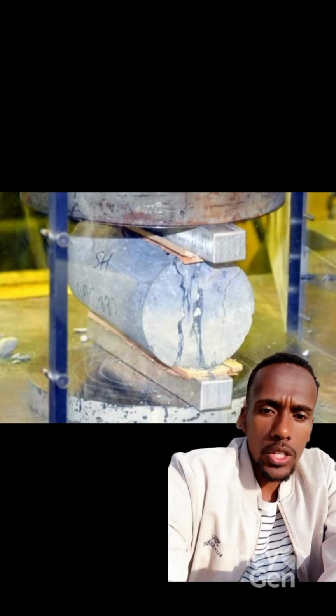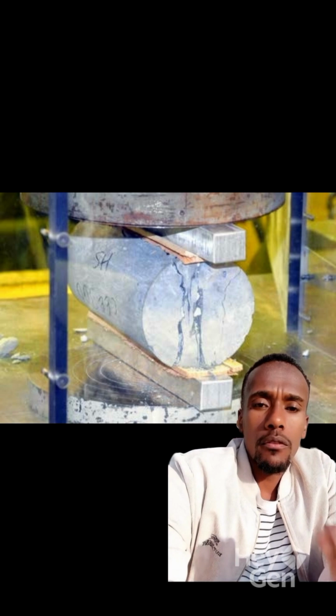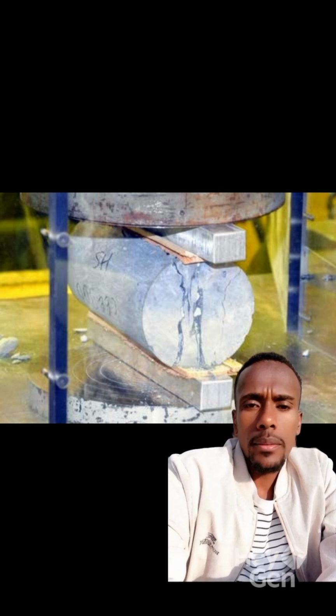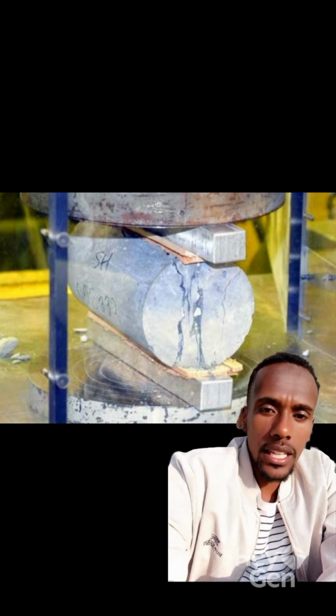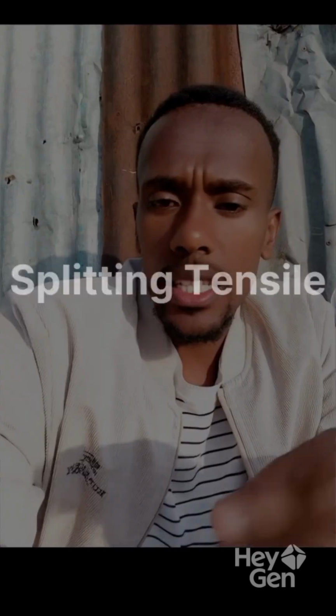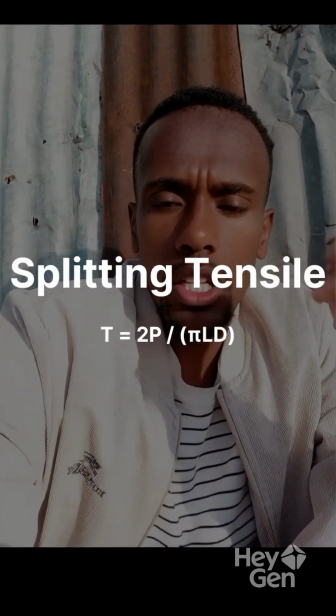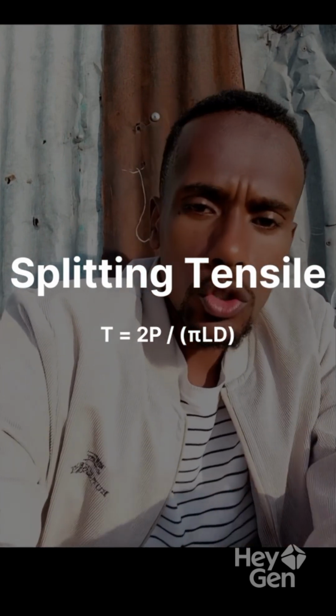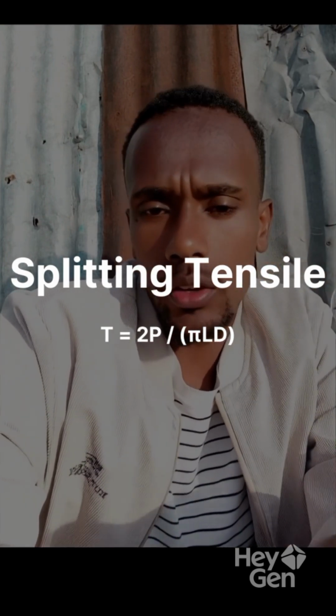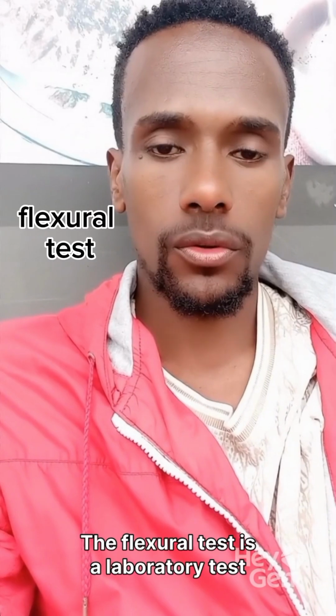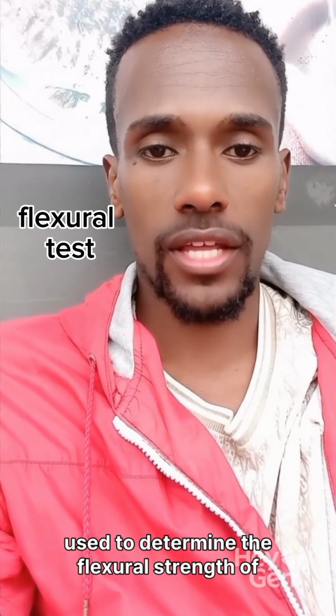The procedure involves curing the concrete cylinder for 7, 14, or 28 days, then placing it horizontally between the platens of a testing machine. A continuous compressive load is applied until the cylinder splits vertically due to tensile stress. Failure occurs due to tensile stress, not compression, and tensile strength is approximately 8 to 12% of compressive strength. This test is also easier to perform than a direct tensile test, making it a crucial method for assessing concrete structural integrity. The flexural test is a laboratory test used to determine the flexural strength of concrete.